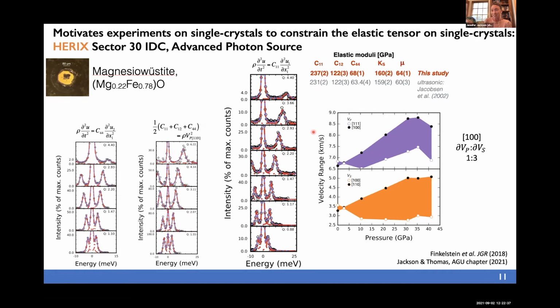But what we found with increasing pressure, which was really quite exciting and surprising, is the extreme level of anisotropy, or the extreme magnitude of anisotropy. So see the P waves appear at the top, the S waves by almost 60% anisotropy, in particular the 100 direction. And so using this information, we explored this possibility in a chapter that I recently published with Tina Thomas, an AGU chapter on the D double prime layer.